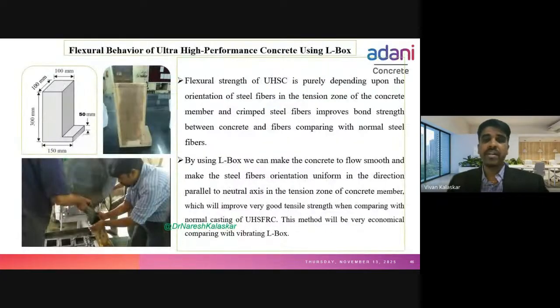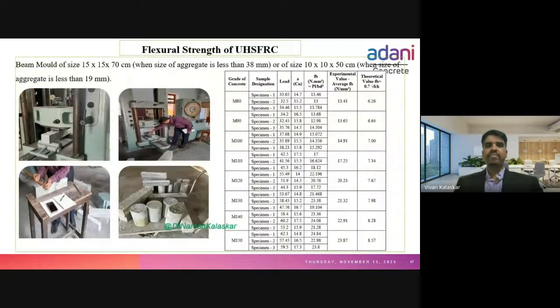This flexural behavior of ultra high performance concrete using L box, I will take up in some other session, because this is also one of the important studies where the fibers play a major role in improving the flexural behavior of UHPC. This is the flexural strength we have checked for UHPC on UTM, Universal Testing Machine, where for M80, we have a formula in the code, that is 0.7 under root fck. For M80, the value will be 6.26 as per code, but for UHPC we got 13.41.